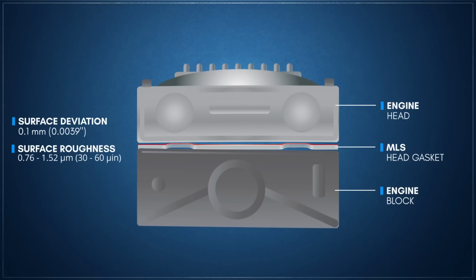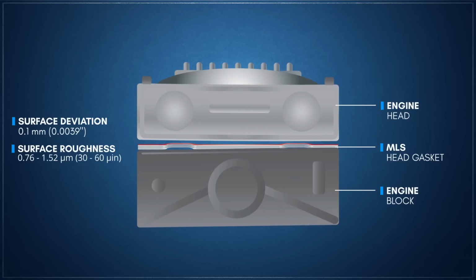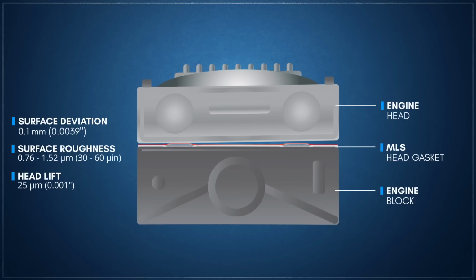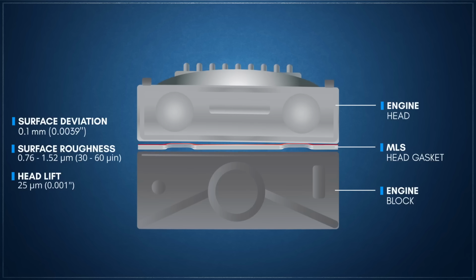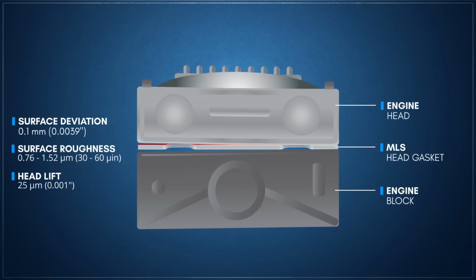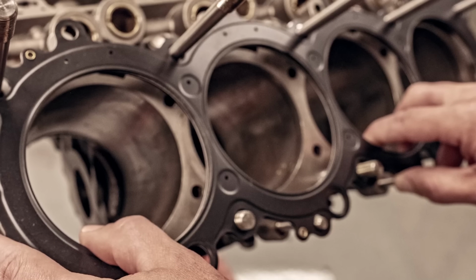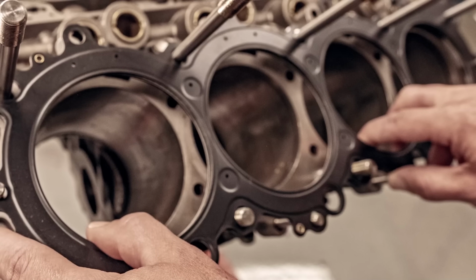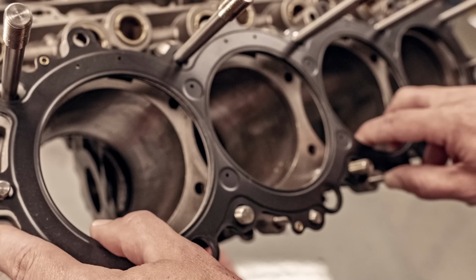This spring effect is so resilient that MLS gaskets are capable of tolerating combustion forces that can lift a head as far as 25 microns or about 1/1000th of an inch from the block. This also had the side effect of requiring no head bolt retorquing maintenance. This layer structure even allowed for additional mechanisms to be embedded within intermediate layers of the gasket, especially for performance applications.